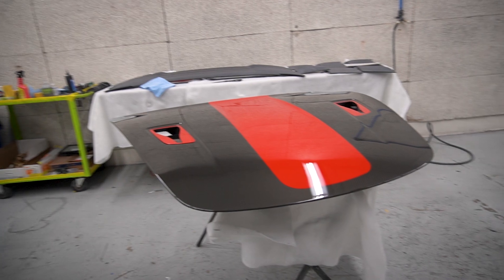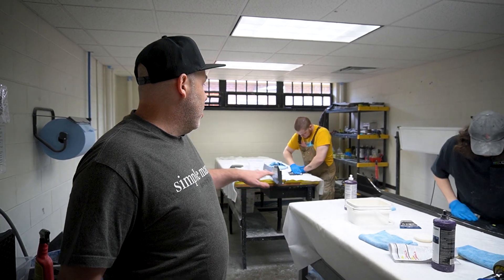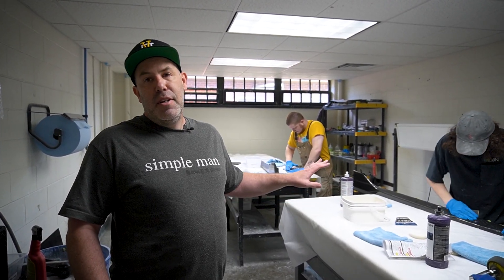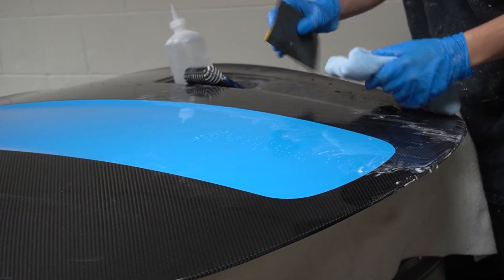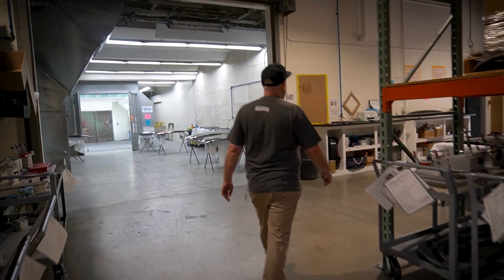We're going to head off to the last step before final inspection, which will be the polishing room. The guys here are actually hand wet sanding, getting all the orange peel out, getting any dirt, debris, or anything else that would be considered unsightly. Once that's been done, they'll run a polisher through all three steps of the compound process. It goes through this rigorous check looking for things like micro scratches, orange peel, any kind of defect that would be considered non-conformant to the customer. Our standards are very high — they go back and forth through inspection and polish until they're absolutely perfect.